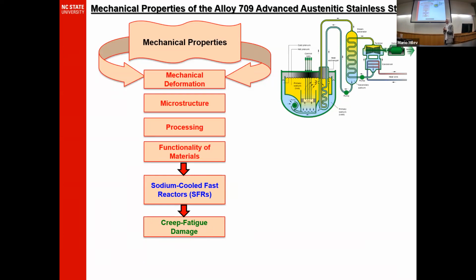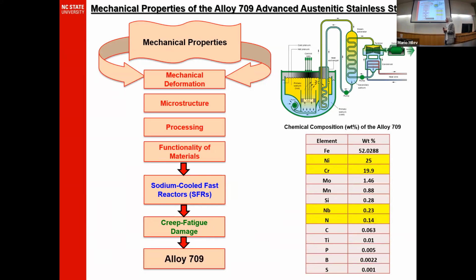One of the candidate structural materials suggested for use in sodium cooled fast reactor, due to its interesting mechanical properties, is the alloy 709 advanced austenitic stainless steel. It includes 25% nickel, 20% chromium, is strengthened by niobium and stabilized by nitrogen. Alloy 709 exhibits interesting mechanical properties like good creep properties, corrosion resistance, high thermal stability, and high temperature strength.